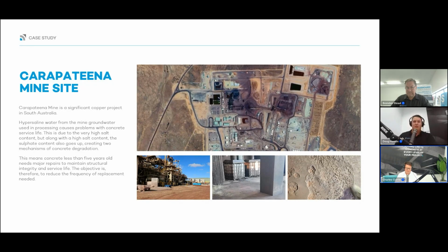So all the washdown water can be up to 7 times the salinity of seawater. So you can imagine what that does to the concrete. It not only permeates through the concrete and attacks the reinforcing steel, but because it's so strong, it actually attacks the surface of the concrete as well. And they get degradation within 5 years there. So this is a perfect example of looking at the environment, looking at the conditions that a structure is going to be in, and designing for that.